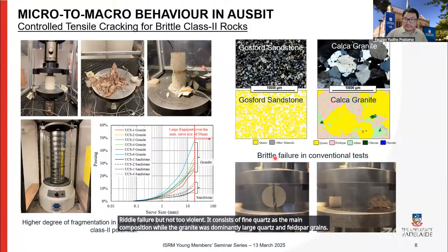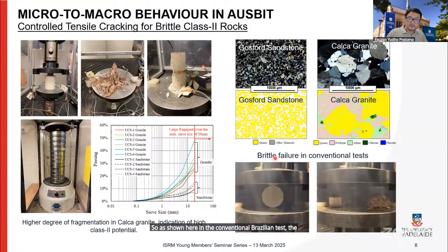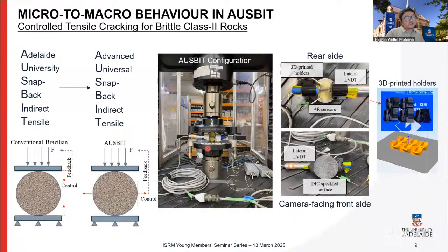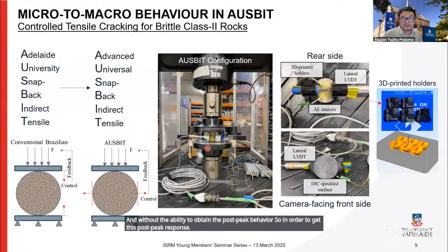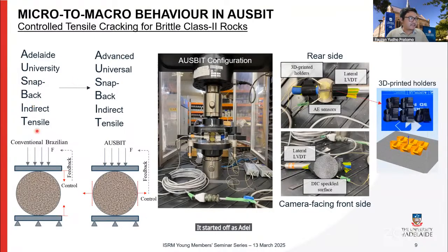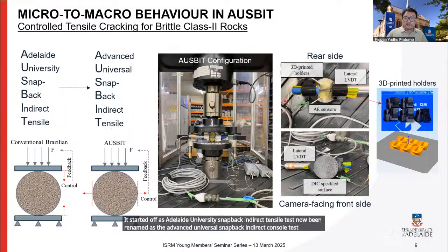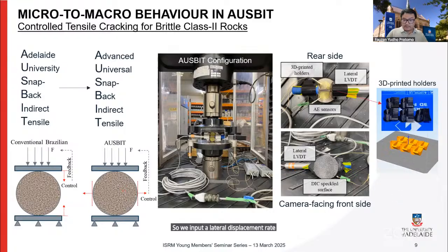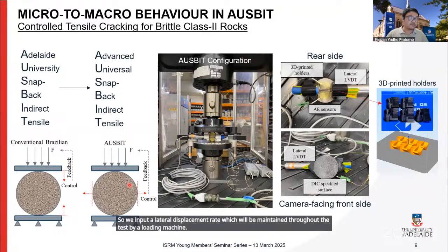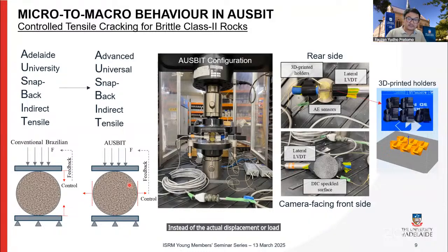So as shown here in the conventional Brazilian test, the brittle failure will occur as shown here, without the ability to obtain the post-peak behavior. So in order to get this post-peak response, AUSBIT was used, which was developed a few years back within our research group. It started off as the Adelaide University snapback indirect tensile test, now renamed the Advanced Universal Snapback Indirect Tensile Test. In AUSBIT, the lateral deformation, measured by an LVDT placed across the diameter, is used as feedback for the loading machine. So we input a lateral displacement rate, which will be maintained throughout the test by the loading machine, instead of the axial displacement or load control in the conventional test.